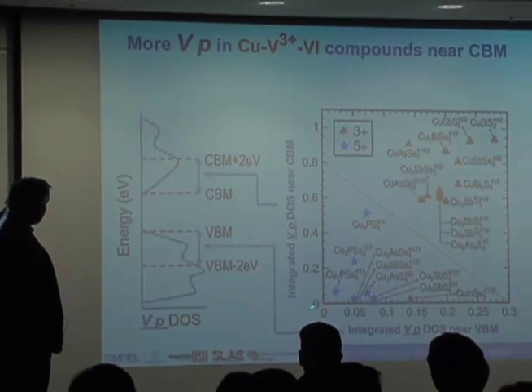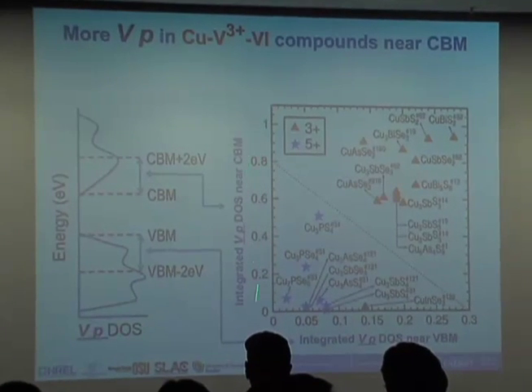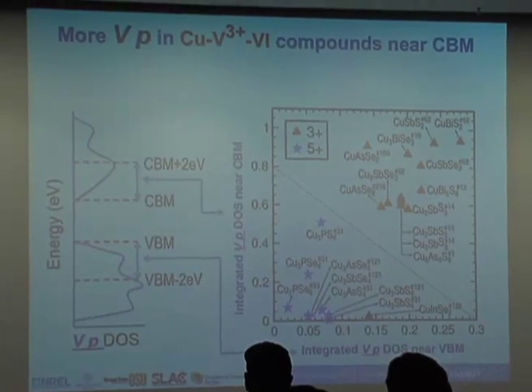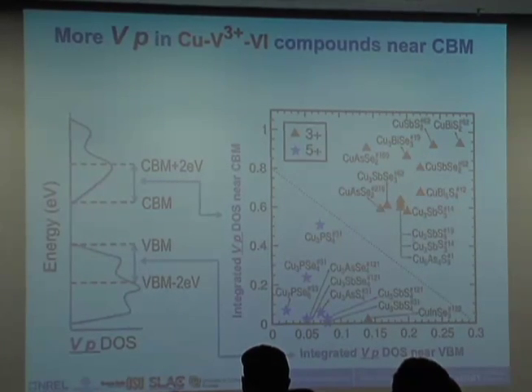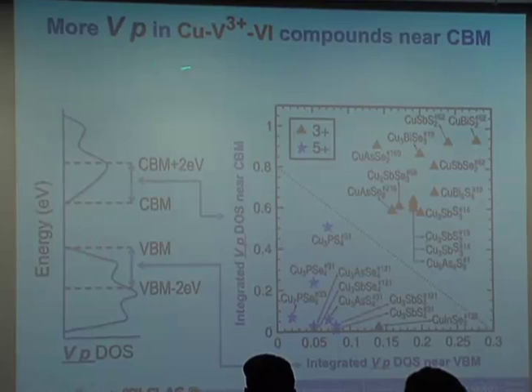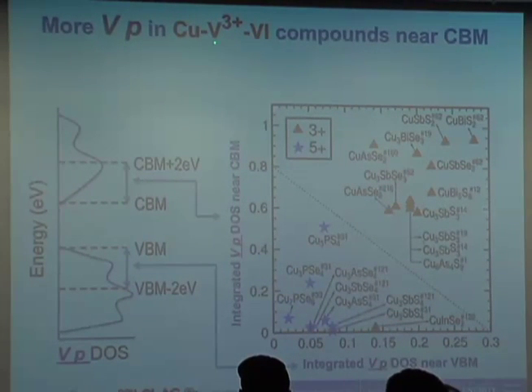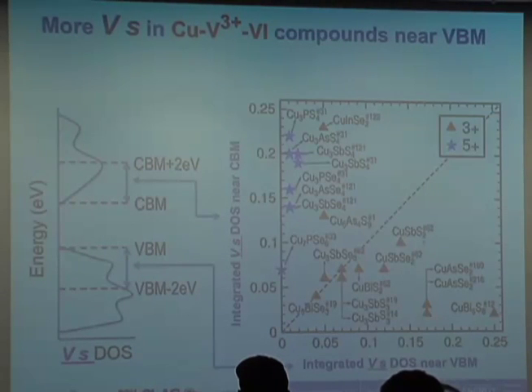And if you just integrate the density of states of the conduction band for the P, both near the valence band and the conduction band, you see very quickly that there's more P in the copper, in the group 5 3+ system here. And if you go look at the S content, you actually see that there's a lot more S now in the valence band. So we've actually been able to show both theoretically and experimentally how we might manage and understand absorptivity in inorganic thin films, and how that absorptivity correlates with respect to the densities of states of both the conduction band and the valence band.